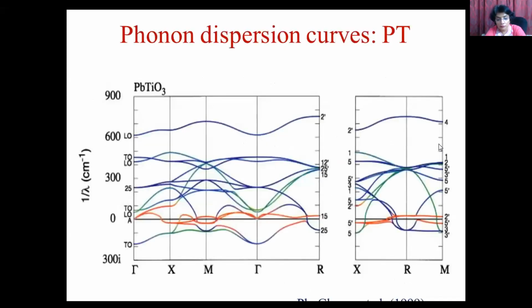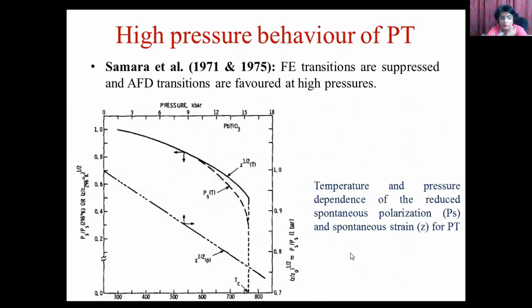Now, if we see the phonon dispersion curves for lead titanate, here we can see that it has very strong zone center optical phonon instability. At the same time, it also has weak zone boundary phonon mode instability. Here we can see. But this P4mm phase is obtained directly as a result of instability of only the zone center optical phonon mode.